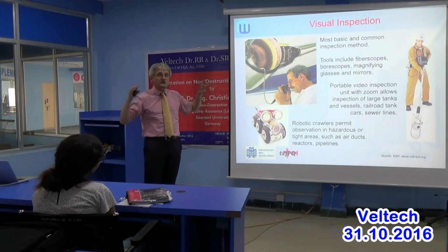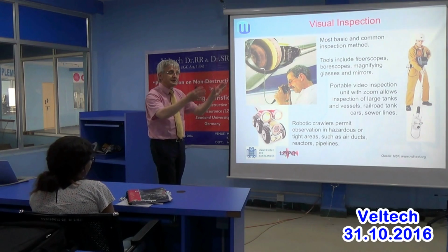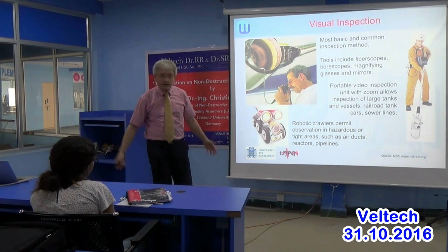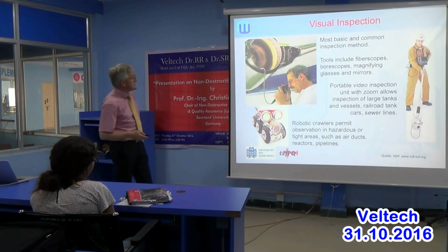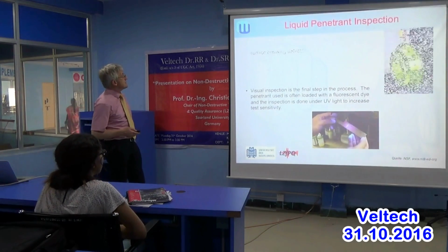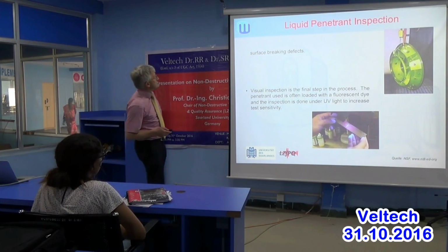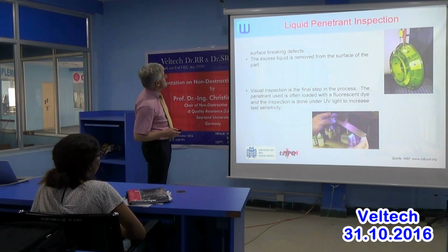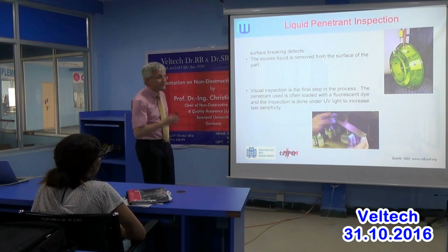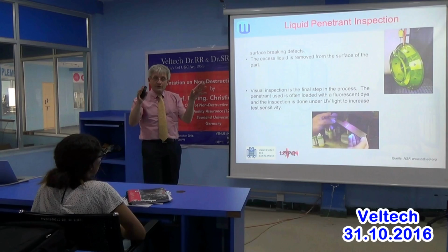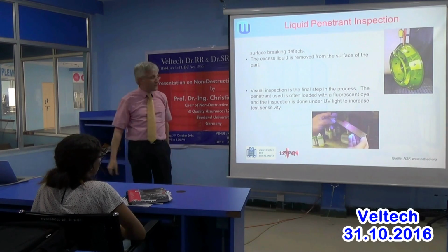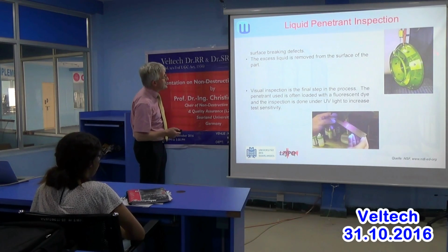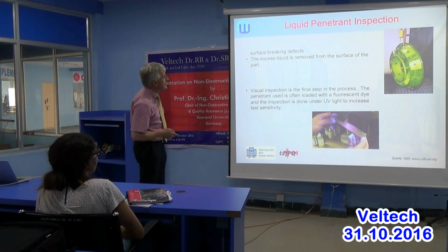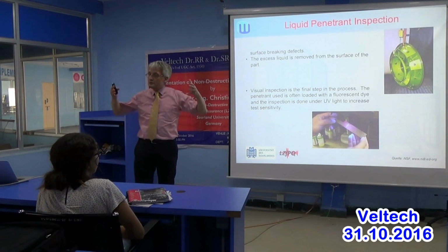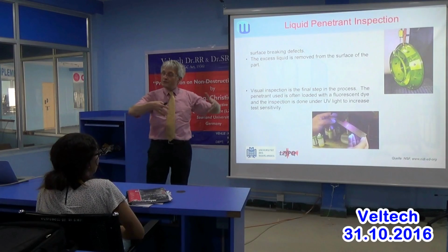So you have a robot which somehow goes through a pipe and inspects the pipe visually. Again, there's a variety of techniques emerging there. Then we have liquid penetrant. Liquid penetrant is basically a very, very fine dispersing liquid, and we wet the whole component with that liquid. This liquid will eventually go into the cracks, if we have cracks on the surface